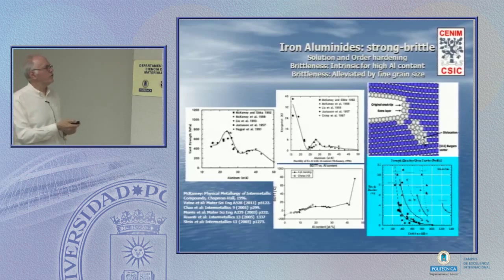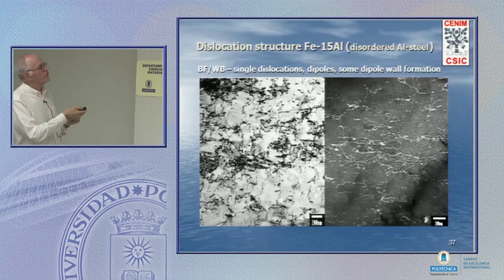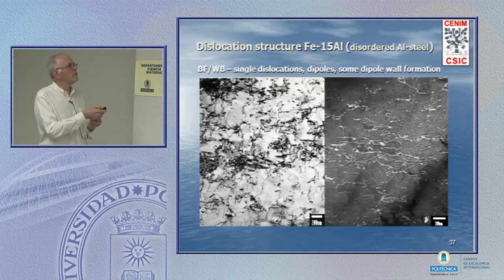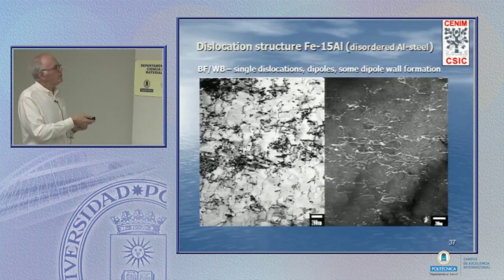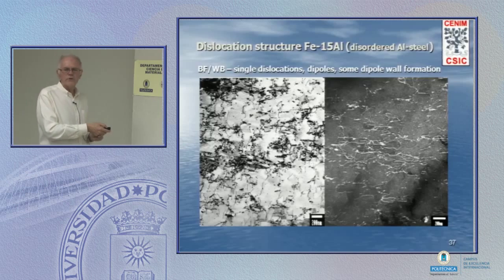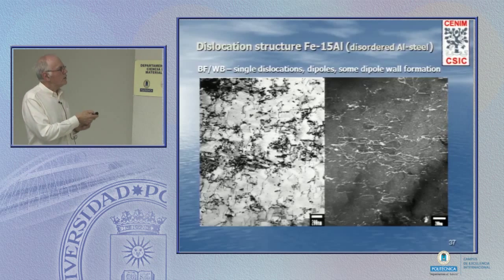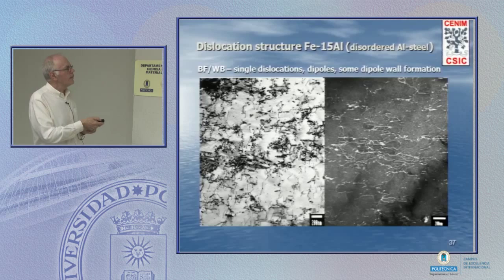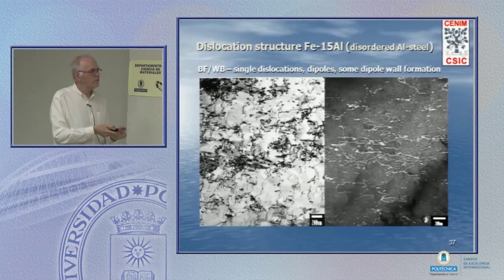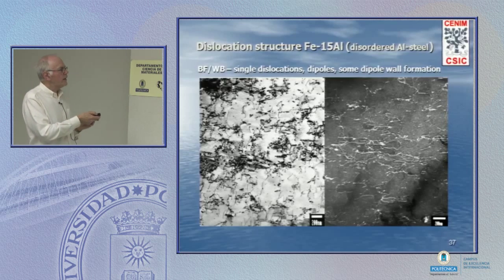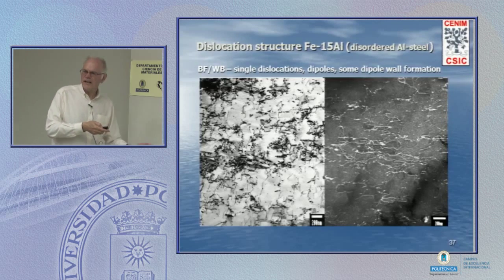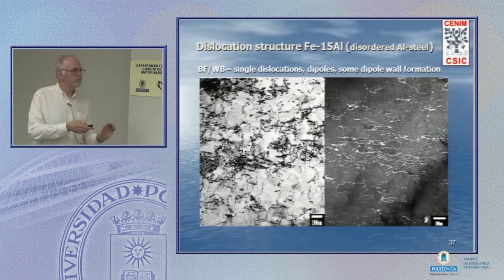Just to show you a couple of the dislocations we've been talking about. This is iron with aluminium in disordered solid solution. It's a small amount of aluminium, and what we've got is a disordered lattice, very much like iron itself. So here we're looking in bright field and in dark field. Here what we see are the single dislocations exactly as in steel, and perhaps the beginning of a dipole wall structure with some dipoles, some debris in the background, exactly as if we were deforming pure iron.